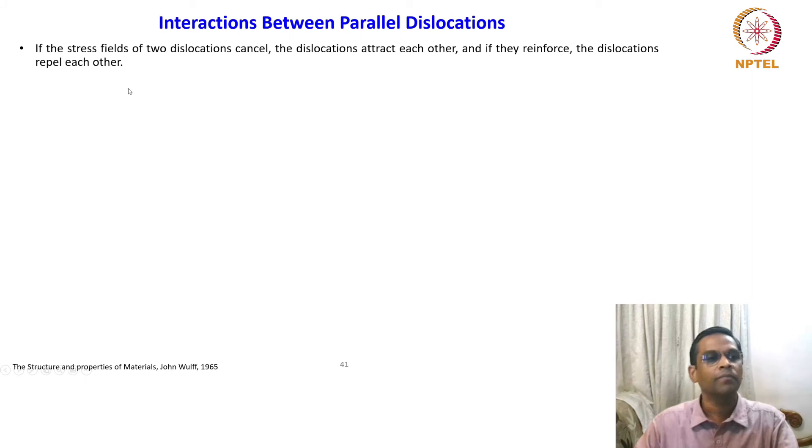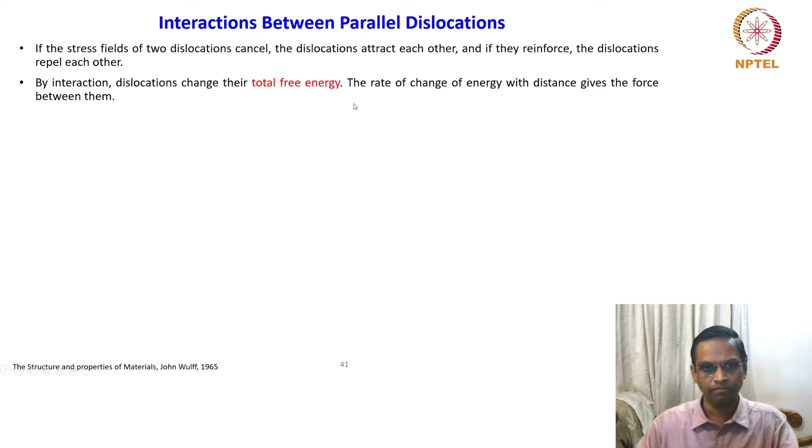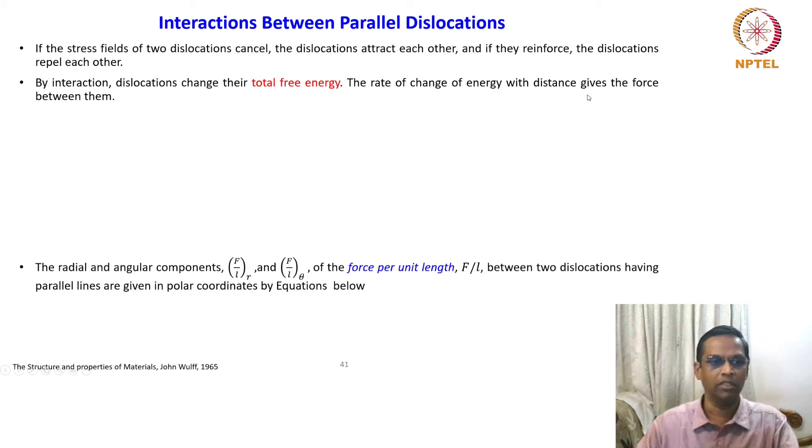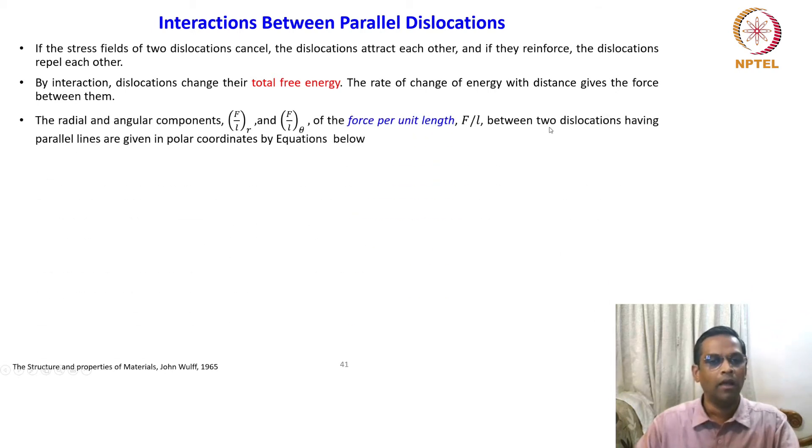If the stress fields of two dislocations cancel, the dislocations attract each other, and if they reinforce, the dislocations repel each other. By interaction, dislocations change their total free energy. We are looking at the rate of change of energy with distance, which gives the force between them. Please understand that we are looking at the rate of change of energy with the distance of a dislocation.